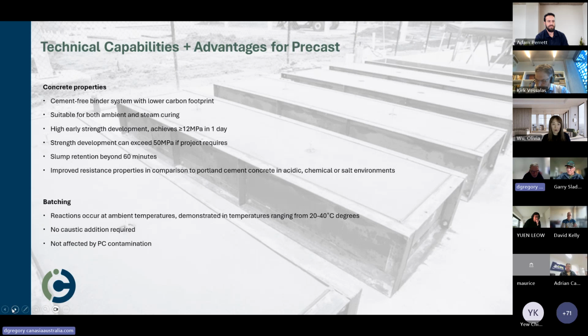As I've said, we do all our reactions at ambient temperatures. There's no caustic contamination. We have done our trials in existing cement-based concrete plants, and we've shown that the performance is not adversely affected by cement contamination. Actually, there are some beneficial effects in one-day strength of having small percentages of cement around.